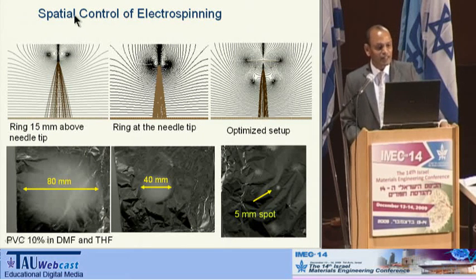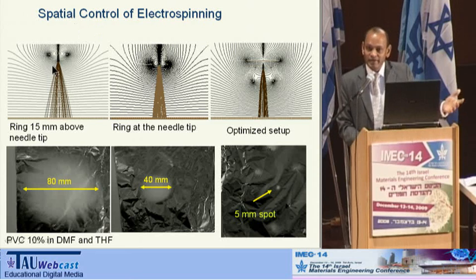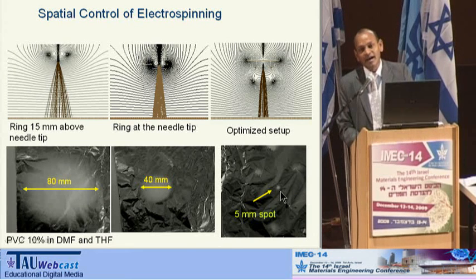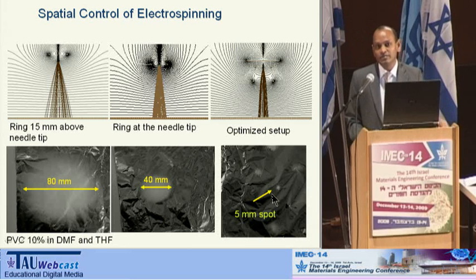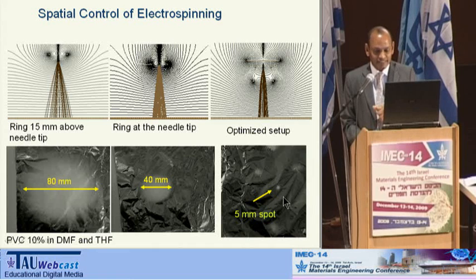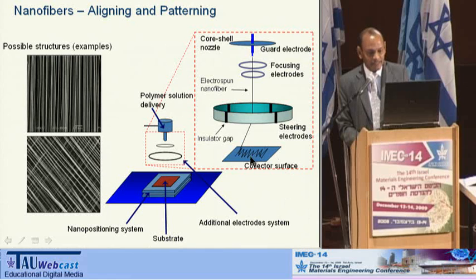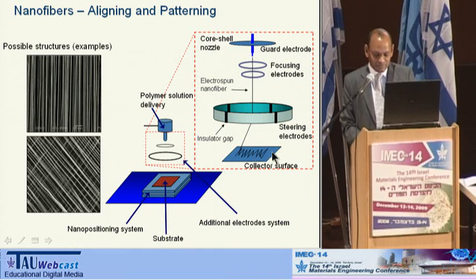And by further controlling the spatial control of the process, by using electromagnetic systems, you could actually control the spot size. And you can see this is less than 5 millimeter spot size. This is being used to produce next generation dental implants. My collaborator in the Faculty of Dentistry is using this system to improve the quality of the adhesion between the dental implant and the host bone tissue. And of course, you can also play with it further. You can start writing these fibers in a specific way. It's pretty early stage, but that is also a direction that is feasible.